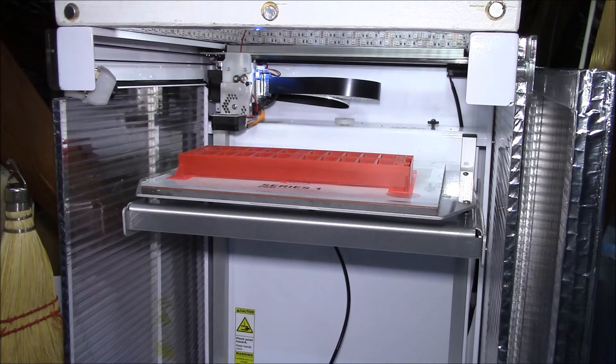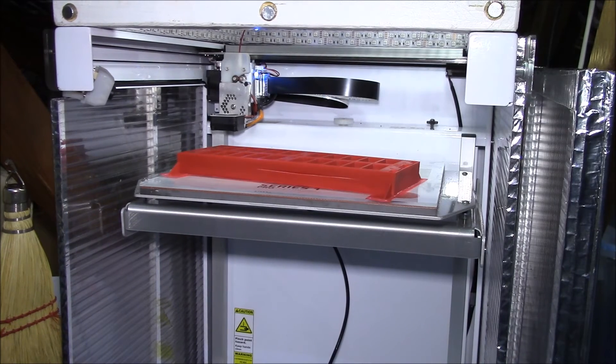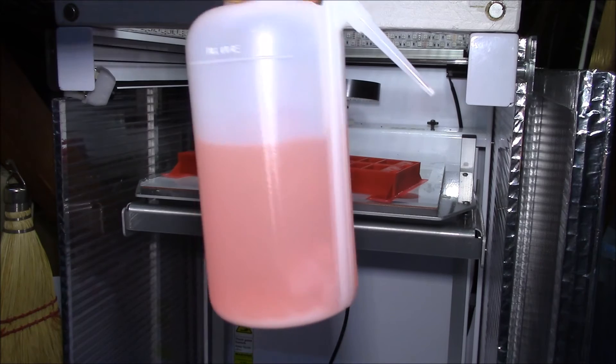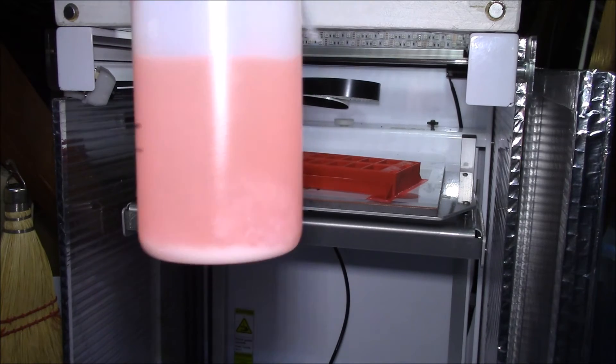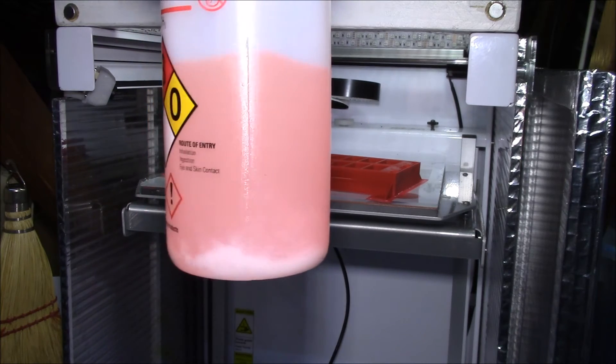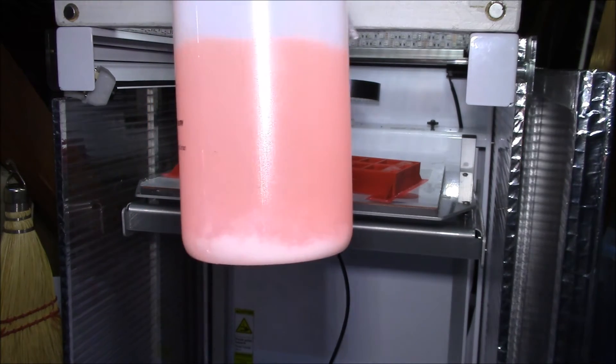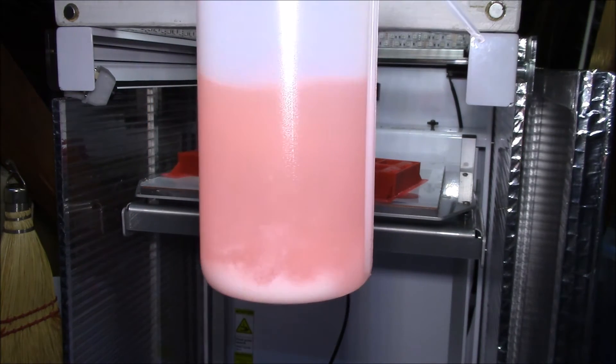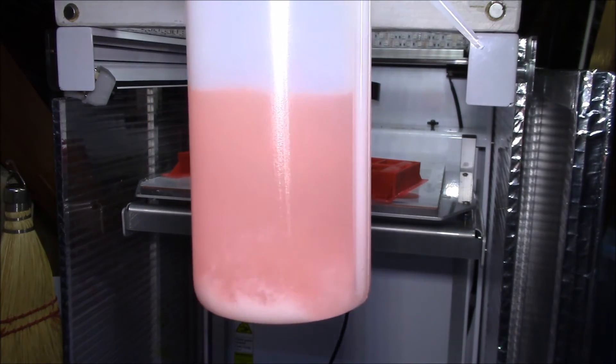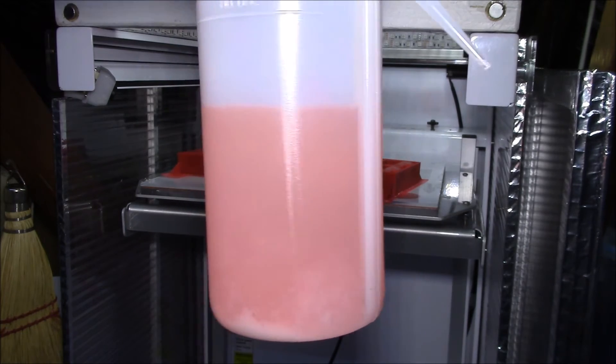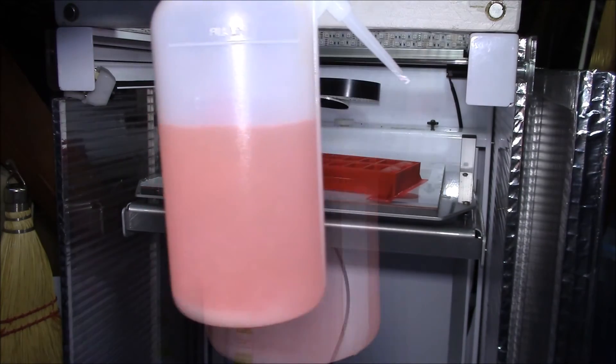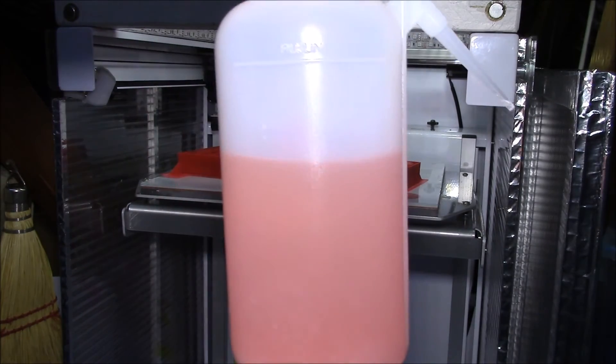That I think is my magic recipe for printing ABS. The other thing I have been doing is I use my ABS juice, so that's with some red filament in there so just a very light pink color. Then I put three coats of that ABS slurry on there, drying in between.